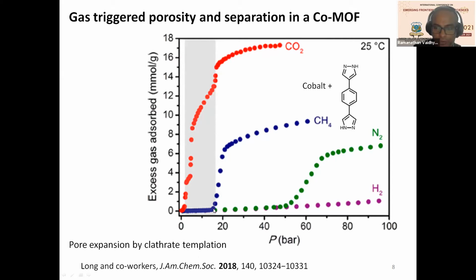So to give you a feel for it, our atmospheric pressure is 1 bar. So this is well above the atmospheric pressure. So up to 18 bars, there's no uptake of methane. But then suddenly the MOF changes its phase or structure, and then you're seeing a gushing of methane into the MOF, and then it saturates to a much higher value. You can see 8 millimoles per gram of methane gets adsorbed.